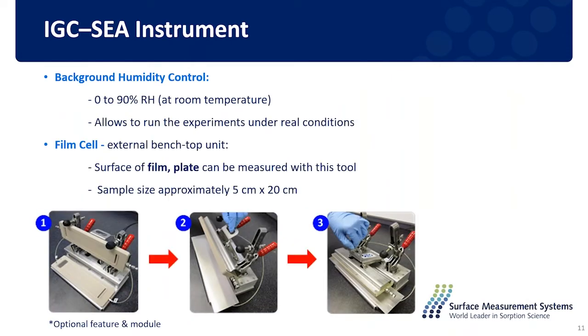And in case some of the sample has a special nature that cannot be broken into pieces to put in the column, we also have an additional feature of the film cell that allows you to put some film sample or the plate sample in the cell to do the analysis with one side of the plate exposed to the vapor molecules. So for example, if you do any kind of surface treatment with a special coating on a plate material, then the film cell is a perfect choice for the analysis.